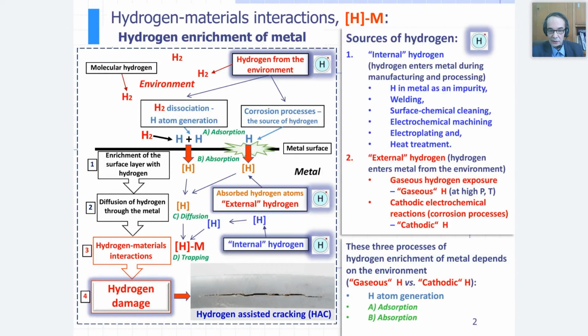As you can see on the slide on the left side, we have a green marked process. The first one is adsorption. The second is absorption into the metal, then diffusion of hydrogen, which is controlled by the stress field in the material. So we have an accumulation and uneven diffusion through the metal, and accumulation in particular areas with a very high hydrogen concentration on typical trapping sites in the microstructure.